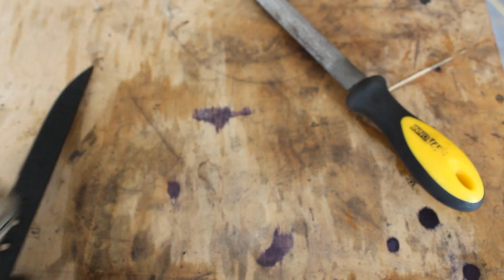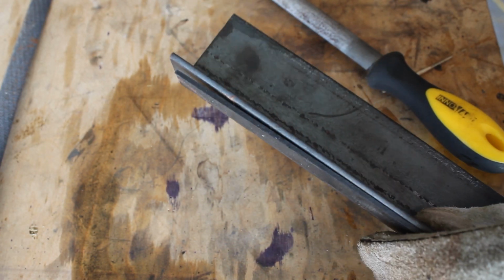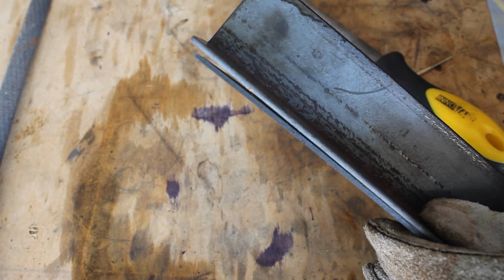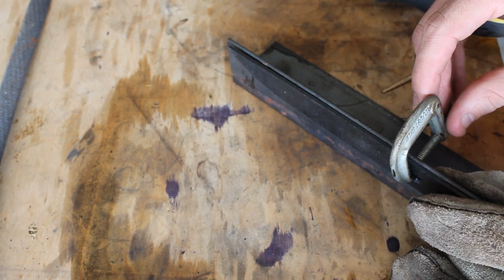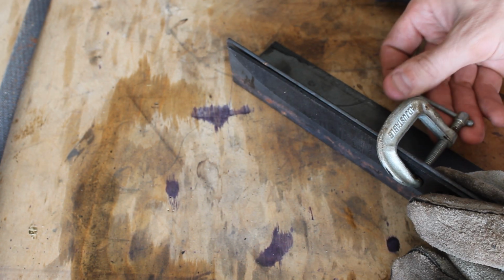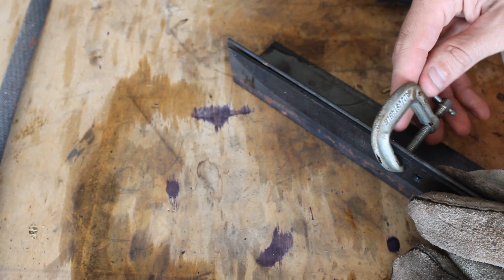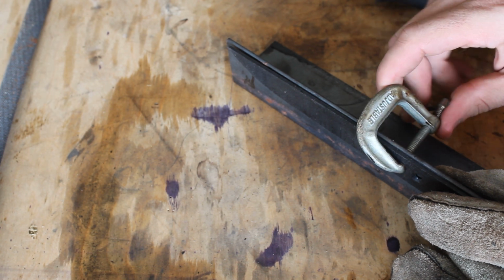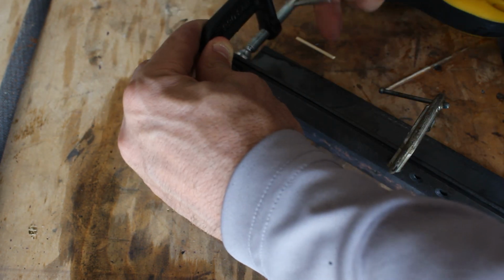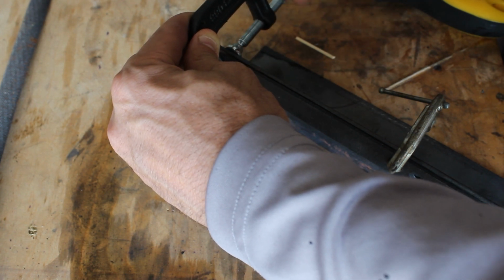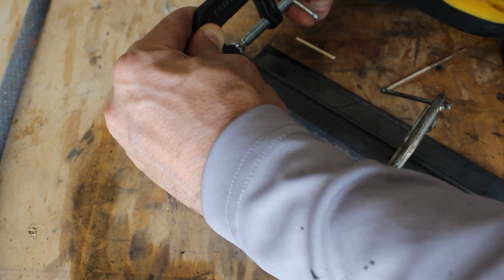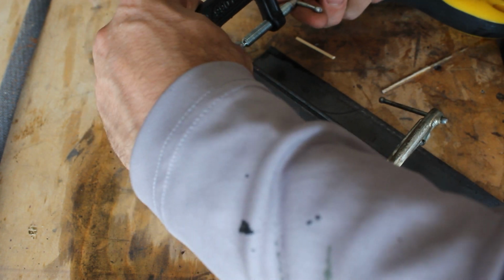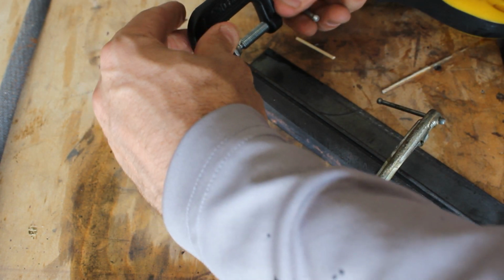The steel hardened quite well, and now I'm going to need to temper it. However, I do have a bit of a bow towards the end of the knife. I'm going to clamp it against angle iron for the temper, and it actually needed a little bit of an overcorrection. So after the first temper of 1 hour at 400 degrees, I went ahead and clamped it slightly past the center, and then after the second temper, it came out perfectly straight.